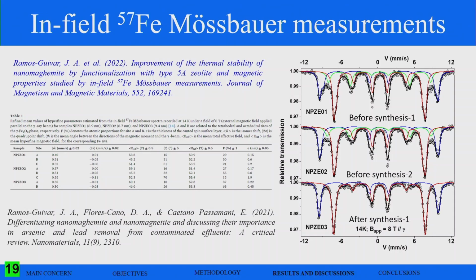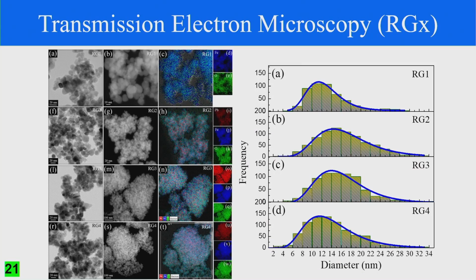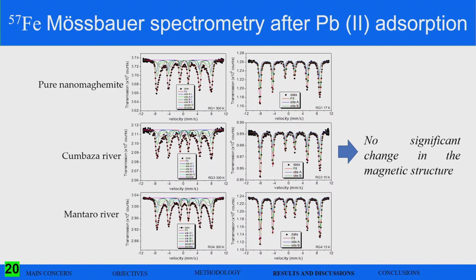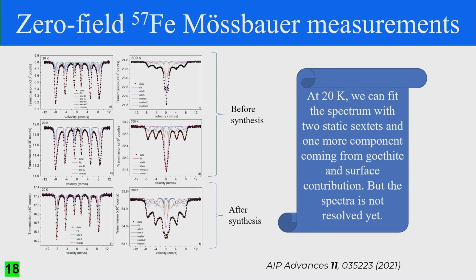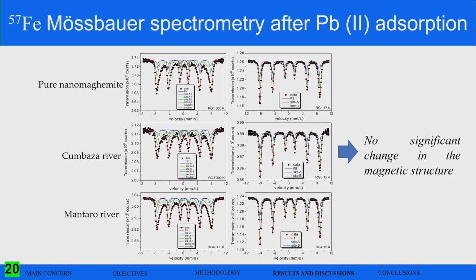If we do not have the possibility to do synchrotron radiation, we can collaborate with colleagues that have in-field Mossbauer measurements. So the repeat sample has the same shape Mossbauer spectrum, as we noticed from the previous one, this one. So it means that we can reproduce the synthesis of the nanoparticles for the pure nanomaghemite.